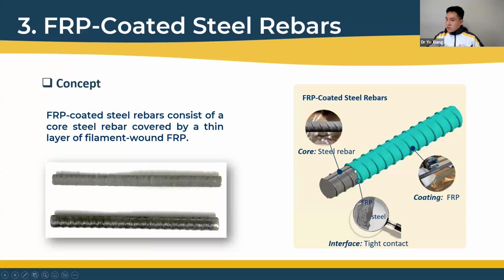Such rebars consist of a thin layer of FRP covered on the core steel rebar. The FRP coating layer was made by the filament winding technique, an innovative use of filament winding with fibers close to the hoop direction of the rebar. This ensures that the FRP coating layer is in close contact with the substrate steel, and the geometry of the ribs of the rebar is largely retained for excellent bond with the surrounding concrete. So this is the concept of the rebar.